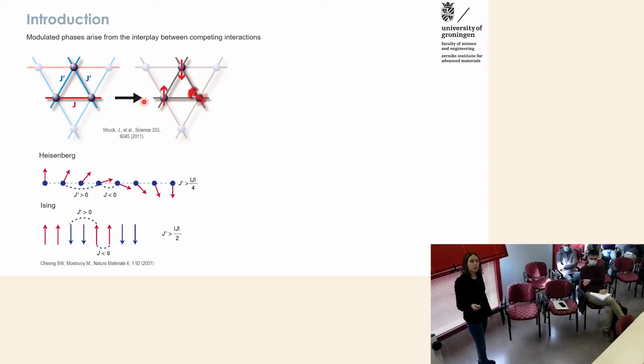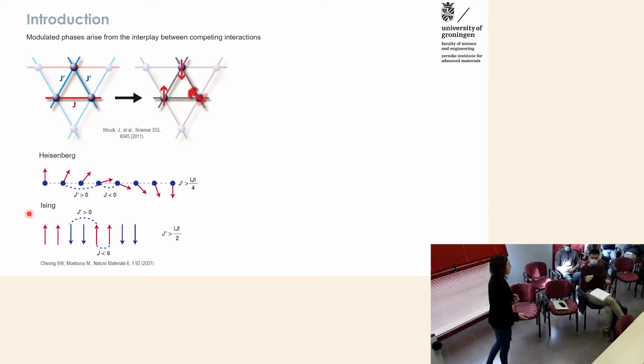So the result is a system where the spins will align in a 120 degree fashion because of the competition between these exchange interactions. And this happens all over in magnetic materials. For example, when we have chains of spins, like in this case, with different interactions between nearest neighbor and next nearest neighbor spins, if these spins are free to rotate in space, they will form some helical or cycloidal spin structure, while in, for example, Ising systems, they will create periodic up and down chains. This would be called the anisotropic next nearest neighbor Ising model, where we have these alternating spins up, up, down, down in the ground state.